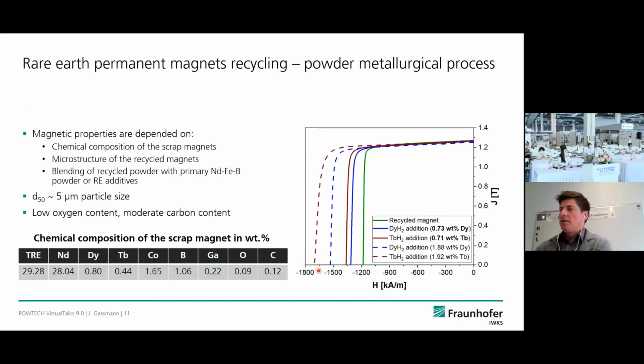So for magnets, the two most important values are the coercivity shown here, which should be as high as possible, and also the remanence, also as high as possible. And the demagnetization curve is dependent on different properties: on the microstructure of the magnet, which is dependent on the powder size one is using for producing the magnet, and on the chemical composition of the magnet, whether it is a heavy rare earth containing magnet or a cerium containing magnet, or a pure neodymium iron boron magnet, which can influence the magnetic properties.